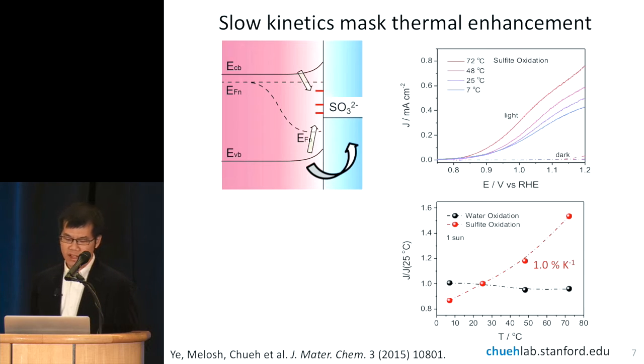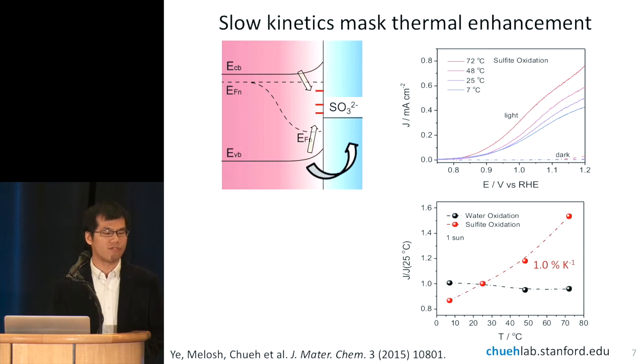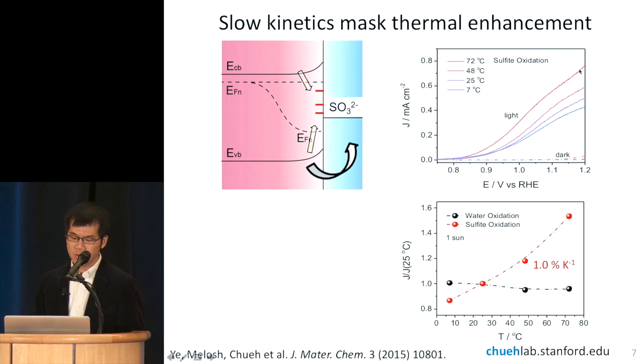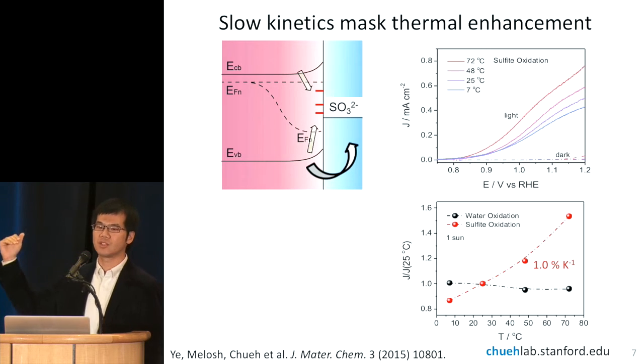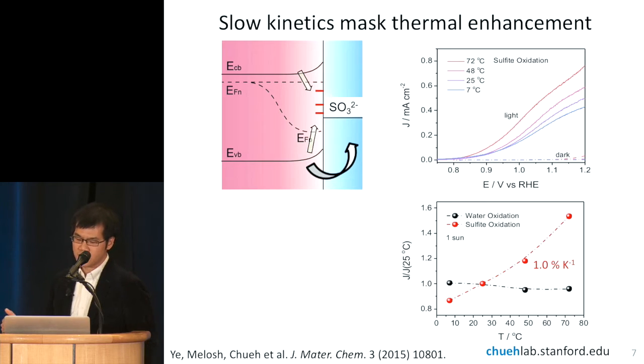Once we replaced the water oxidation reaction with the sulfite oxidation reaction, as you can see here in the top right, the current began to increase with the temperature. The blue line is at 7 degrees Celsius, and the red line at 72 degrees Celsius. You can see the current is slowly climbing. The voltage is still shifting a little bit, but it is much better than the previous case.